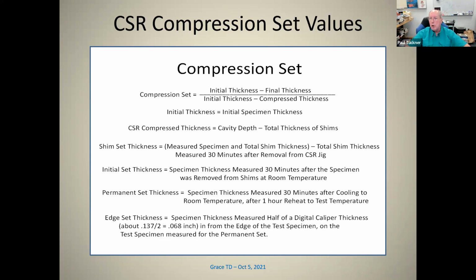So for materials that age non-uniformly by diffusion limited oxidation, you find that the edge set is greater than the permanent set. So it gives you some indication of the uniformity of degradation. All of these 4 different compression set values are useful to give you some information on what's happening with the specimen in the CSR jig.